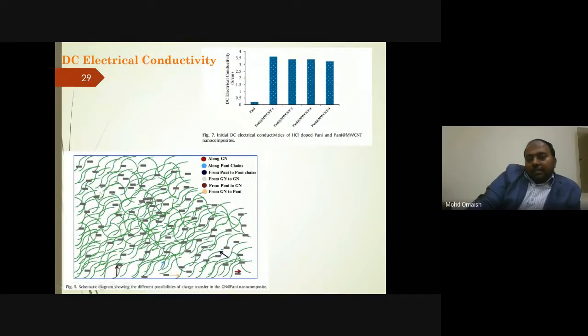This is the DC electrical conductivity of polyaniline carbon nanotubes. Here we see that in the case of polyaniline, the conductivity is much lower, around 0.4 Siemens per centimeter, but on loading with carbon nanotubes, the conductivity increased. On further loading, the conductivity decreased. The amount of filler at which you get the highest conductivity is called the percolation threshold. In this case, I think it was around 1%.